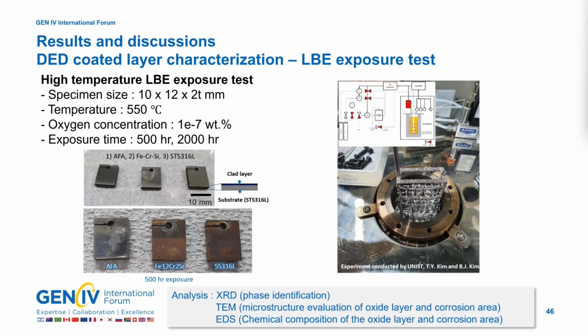Each coated material was evaluated for LBE corrosion resistance in a high temperature LBE environment with controlled oxygen concentration. The samples were exposed for 500 hours and 2000 hours. After testing, XRD and TEM EDS analysis were performed to evaluate the oxide layer on the coated surface.